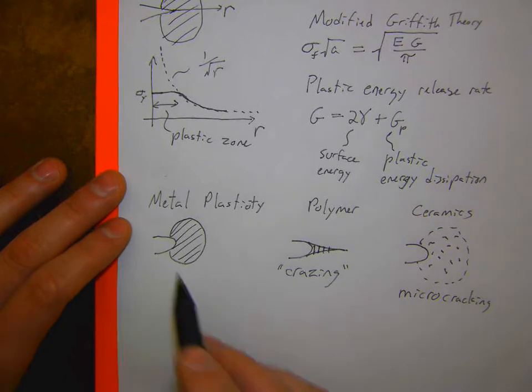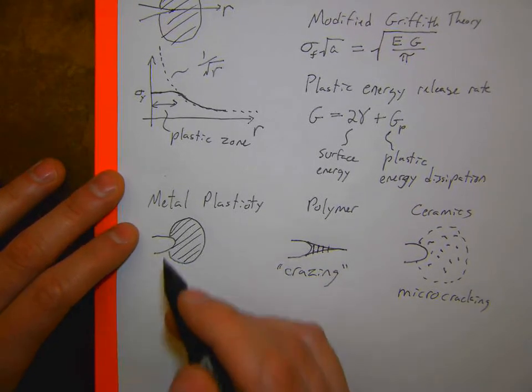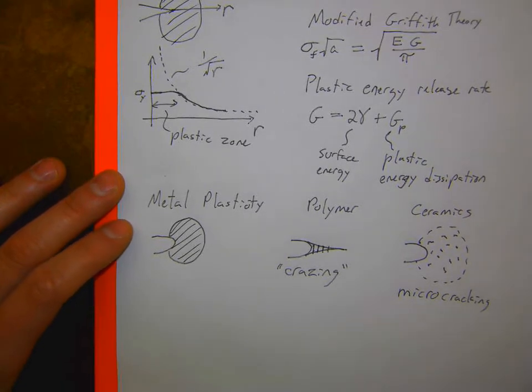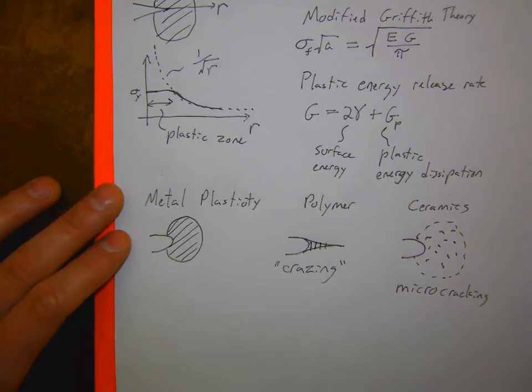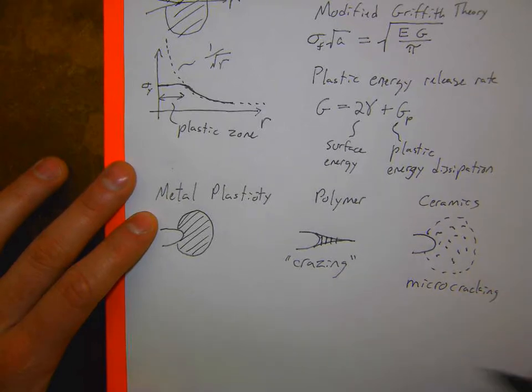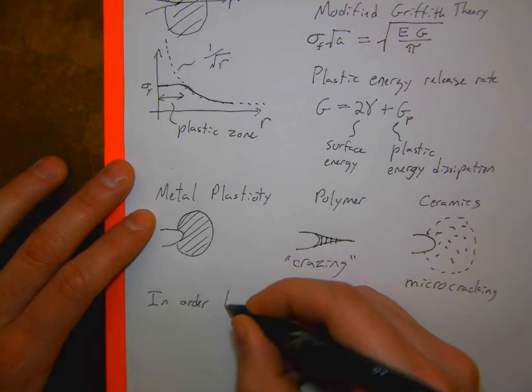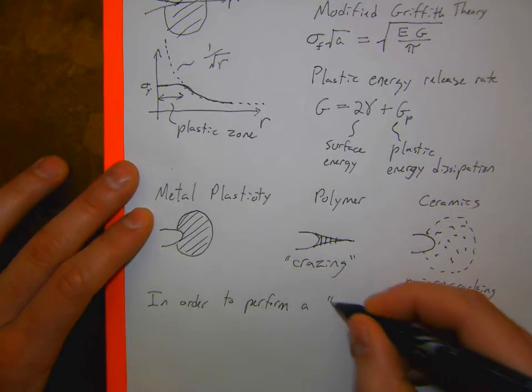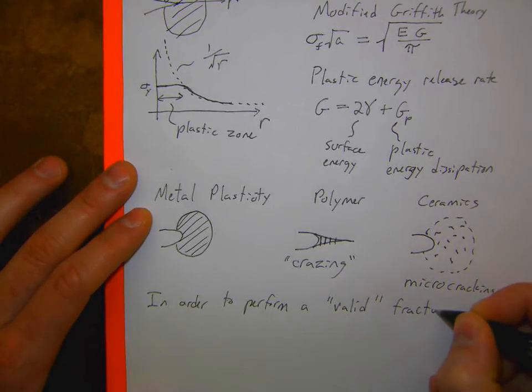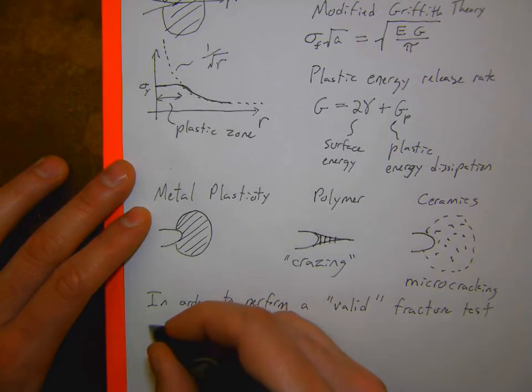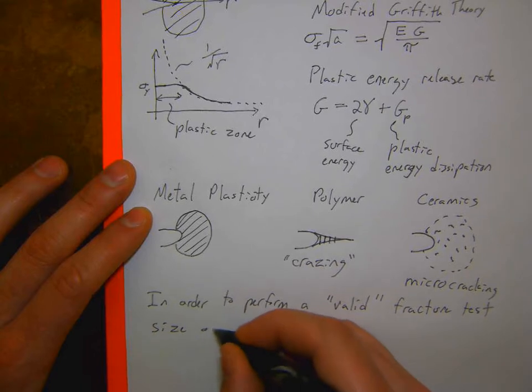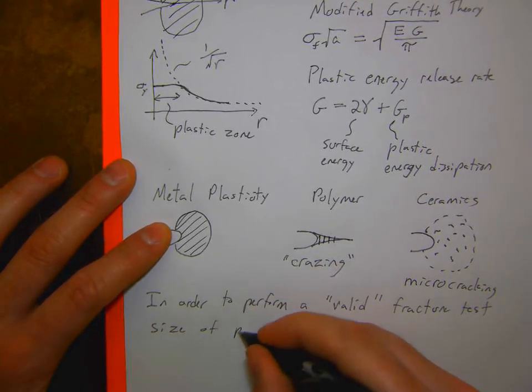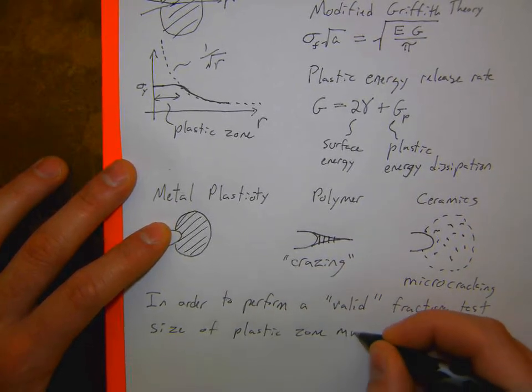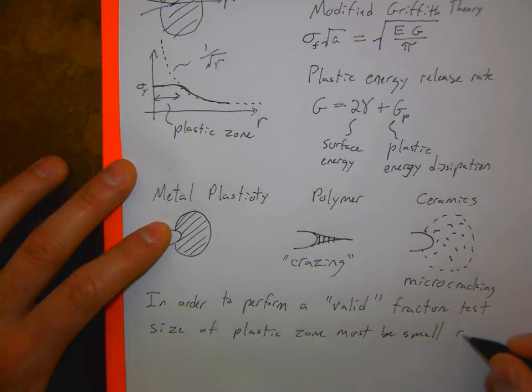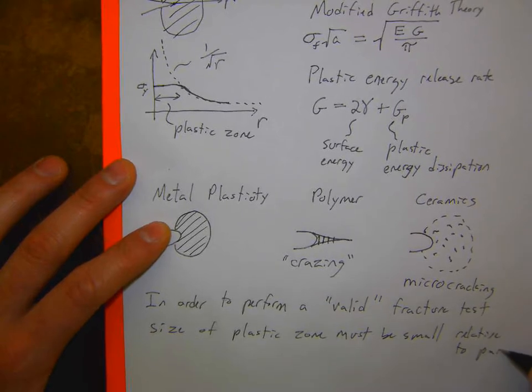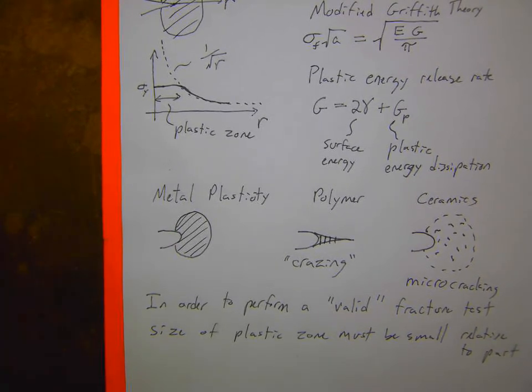Now for our fracture analysis, in order to obtain material parameters, we have to ensure that the plastic zone size is small relative to the total part. So in order to perform a valid fracture test, the size of the plastic zone must be small relative to the part.